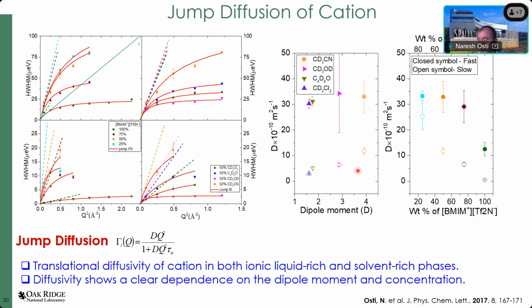The slow process is always the long-range translational process, which is the very important process. The fast process is coming from some sort of in-cage rattling motion, but it's not coming from the long-range translational mobility. The long-range translational mobility comes from the slow process, which shows a strong dependence on the dipole moment of the solvent. As you can see, the higher the dipole moment, the higher the diffusivity. In a similar way, if you increase the concentration of the solvent, you see an increase in diffusivity, because the more solvent molecules, the more they separate the ion pairs. That's why the ions have a chance to move freely, and you get better diffusivity at higher concentration of the organic solvent.